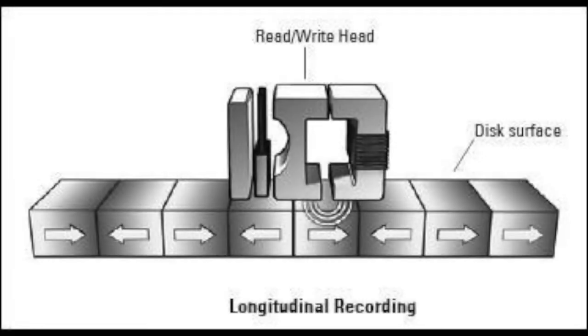Hard drives used to store data in the form of longitudinal magnetic recording, where the magnetic field traveled down the track in the horizontal direction. There is a limit to the data density of this method, since as the magnetized areas become smaller, they require less energy to flip their magnetization. This makes it more probable that fluctuations in temperature can result in unwanted flipping and loss of data.